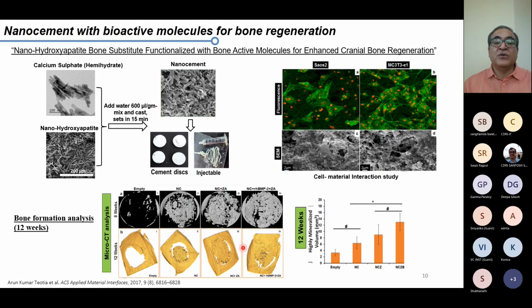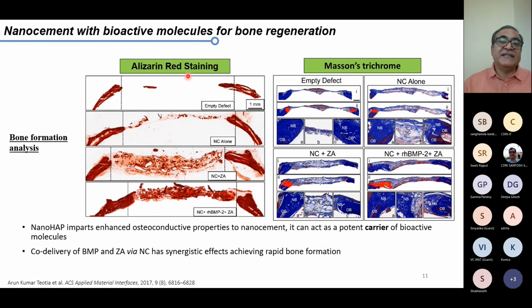In this case, no cells were added, even though you have a limited supply of cells in the cranial part. Still, at the edges of the cranial part, the cells may migrate in. This is the Alizarin red staining to show whether we have calcium nodule formation. You can see the maximum in the last group, which is with the BMP and ZA. And the Masson trichrome stain, which shows the collagen fibrils, again shows that the one with the bioactive molecules has the better outcome.